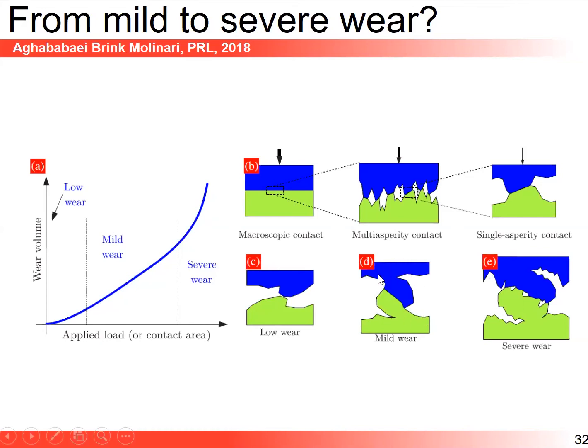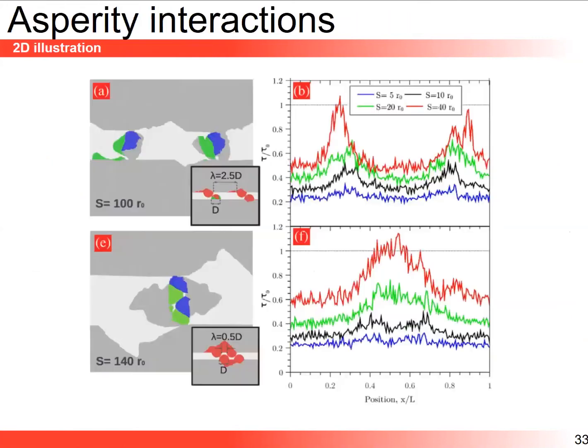And perhaps the transition from mild wear to severe wear is the fact that we will form a debris at a single asperity for mild wear, versus for severe wear, we will englobe several neighboring microcontacts with gaps in between. So it's not anymore the real contact area that matters, but it is the nominal or apparent contact area that matters to form a debris.